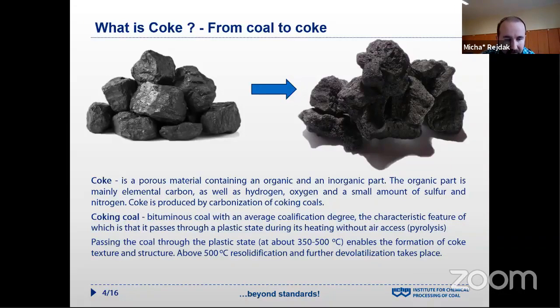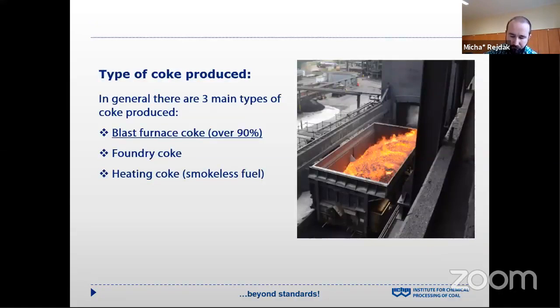It's called the pyrolysis process. Passing the coal through the plastic state, which occurs at about between 350 and 500 degrees Celsius, enables the formation of coke texture and structure. Above this temperature, in general, resolidification and further devolatilization take place. There are generally three main types of coke produced: blast furnace coke, the production of which accounts for over 90% of global production; foundry coke, used for iron and steel foundry, casting of non-ferrous metals, and manufacture of insulation products like mineral wool; and heating coke, used for heating purposes as smokeless fuel.